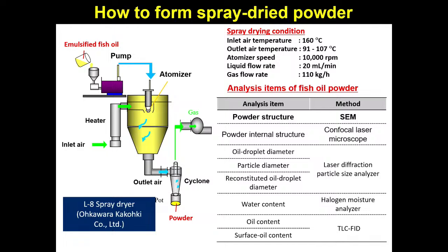The inlet air temperature in industry is 180, 160, 140. But usually in industry you can see the outlet temperature about 90, sometimes below 90. The atomizer speed depends on the nozzle type and atomizer type, and then we can control the flow rate and gas flow rate. Those parameters are important, and then we check the powder structure and properties. But first, please remember, the outlet temperature is about 90 degrees Celsius. These are usually the basic factors.